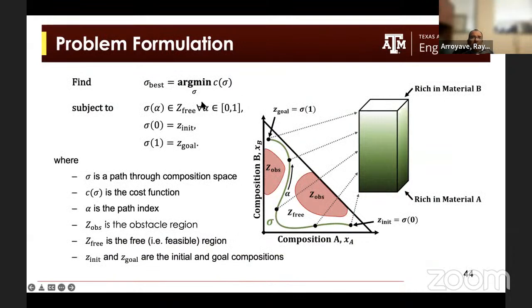Basically, what we do is we try to minimize a particular function, and this function could be a property, or the length of the path or some other quantity, subject to the fact that you start and end at a particular point in the chemical space, and subject to constraints related to the fact that you want to avoid regions in the chemical space that are undesirable, maybe because some phases may form that are undesirable, or because some regions have a low melting point or some other undesirable characteristic. So can we map a trajectory in an n-dimensional space, maximizing or minimizing a quantity while avoiding obstacles?